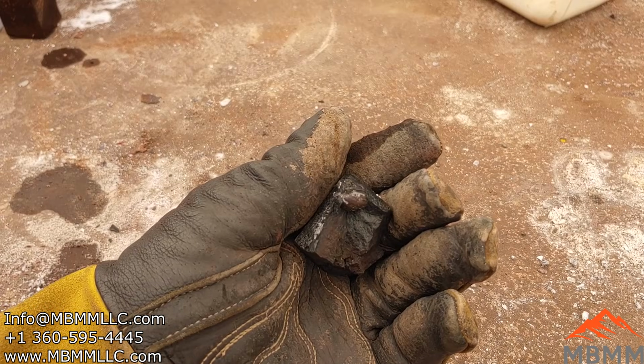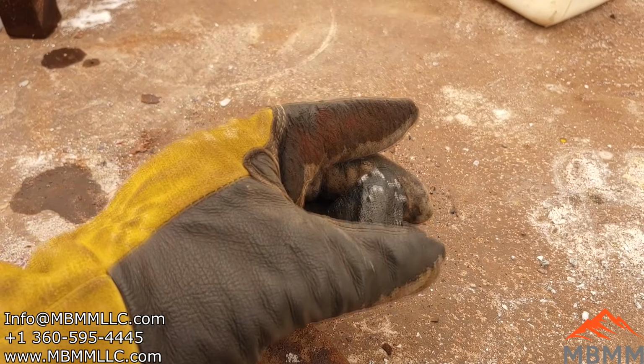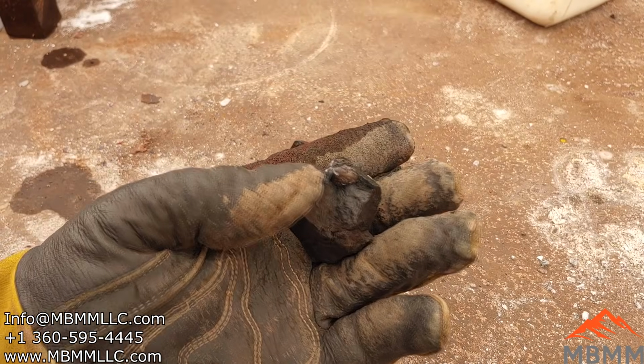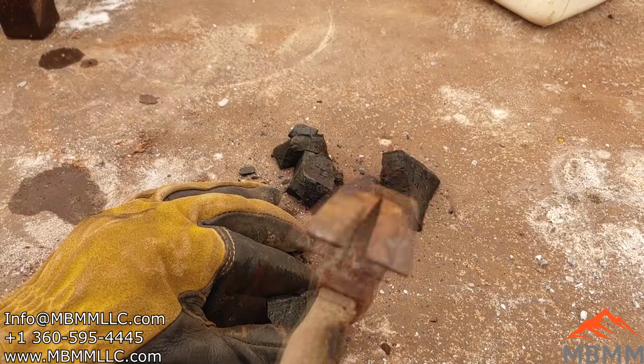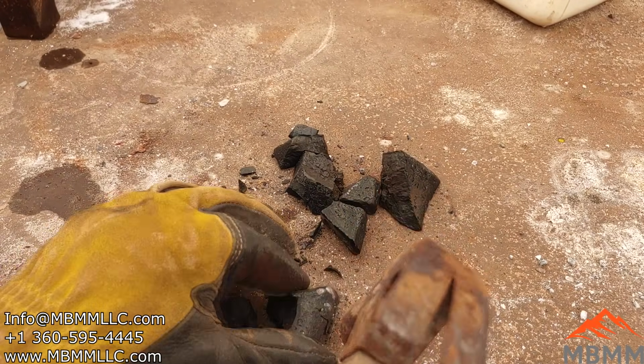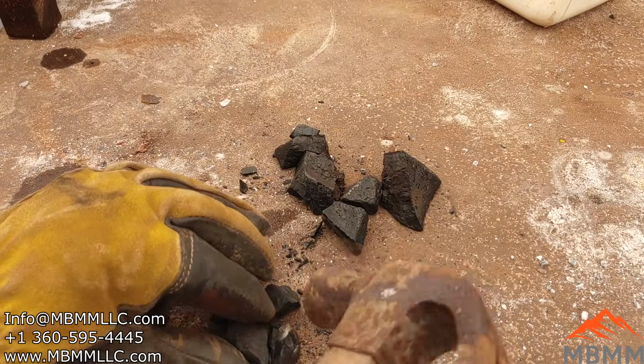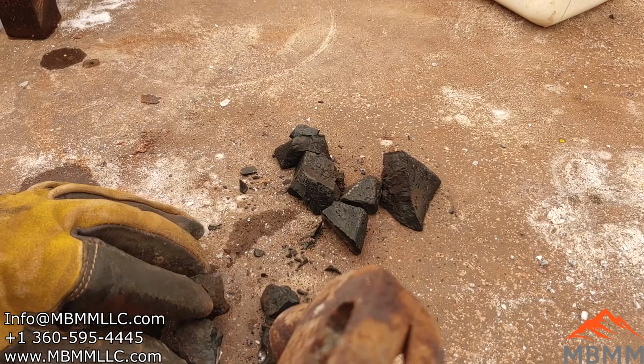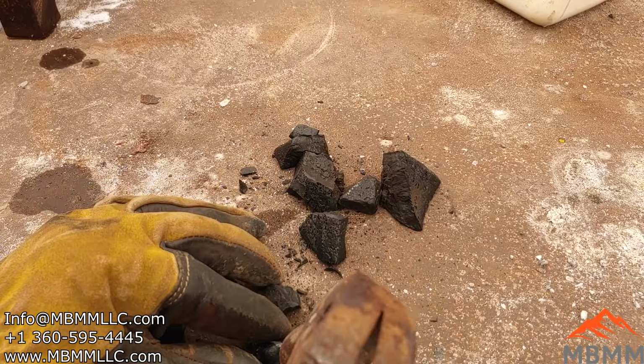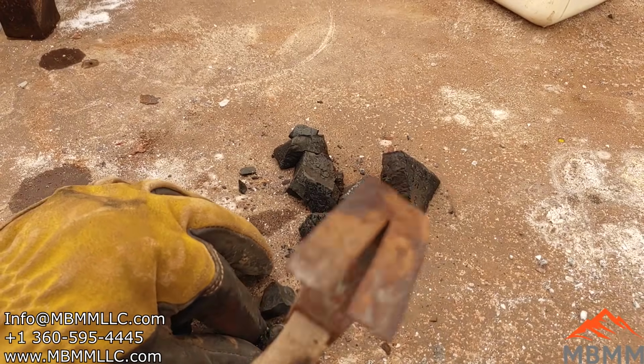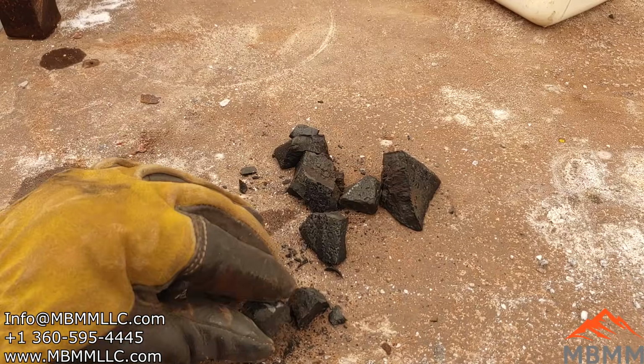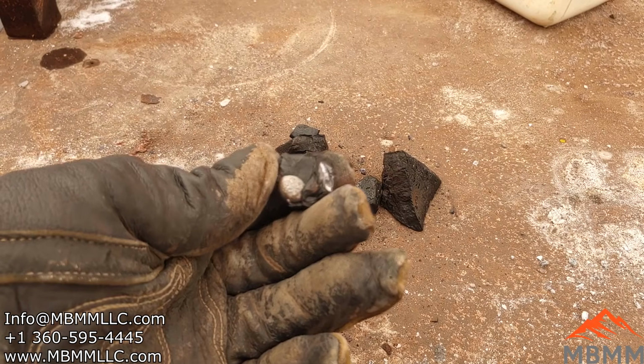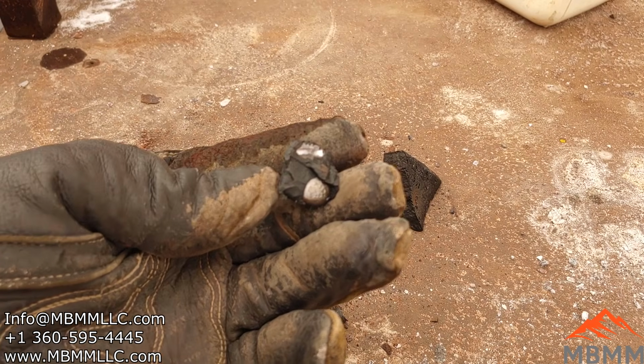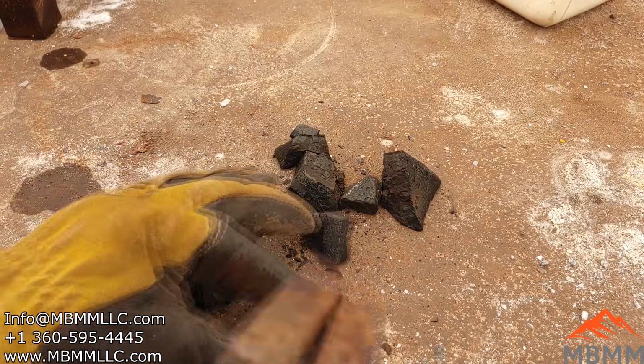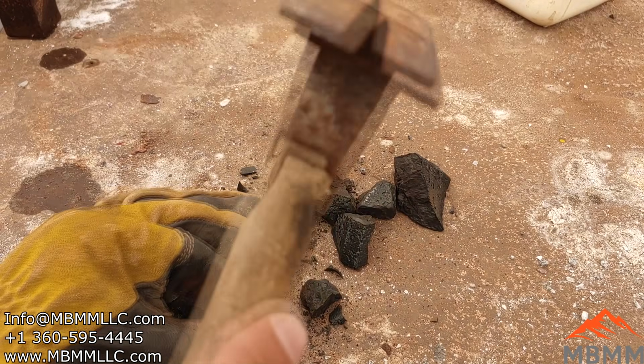Now, one other thing I may have got in the video, but I'll say it now: when you're using a bunch of soda ash, you want to heat it fairly slowly or it tends to boil over. So I held it at about 1850 degrees there for a while to let it do its reaction and get the gases off so it didn't boil over. So it takes a little bit longer, and you just got to be patient. But it's always better to get a good melt with no boiling.